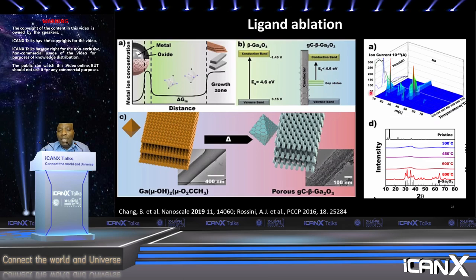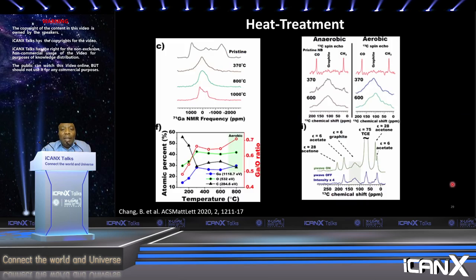And so when we heated this material, of course, we see the loss of the organic matter and we see a loss of crystallinity. And then we recover our crystallinity at about 800. And this aligns very well with the most stable form of gallium oxide, beta gallium oxide. We did quite a bit of characterization, from solid-state NMR, gravimetric, XPS, to understand what is going on, and we were interested in both tracking the carbon and the metal content, whether we treated the samples in aerobic or anaerobic conditions.